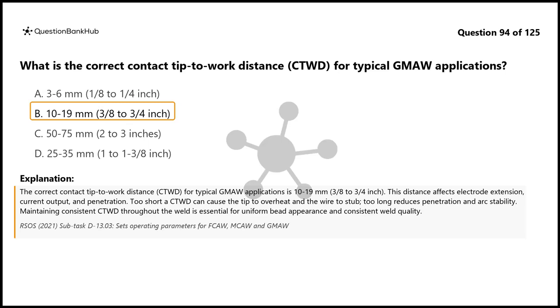Too short a contact tip to work distance can cause the tip to overheat and the wire to stub, too long reduces penetration and arc stability. Maintaining consistent contact tip to work distance throughout the weld is essential for uniform bead appearance and consistent weld quality.